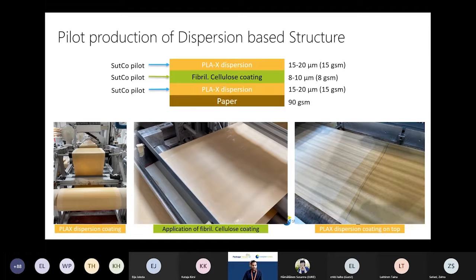So we started with our base paper, applied the PLA-X dispersion, which was around 15 GSM coating layer, and then applied fibrillated cellulose coating on top of that, around 8 GSM again. And on top of that, after drying, we applied 15 GSM of PLA-X coating. And here you can see actually the 3 layers on the paper. So the first PLA-X layer, then in this one here we have the fibrillated cellulose coating, and then we have PLA-X layer on top again.